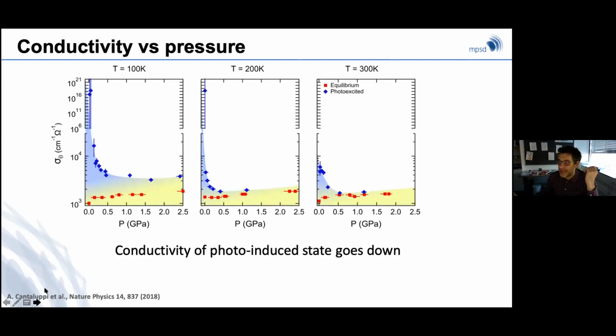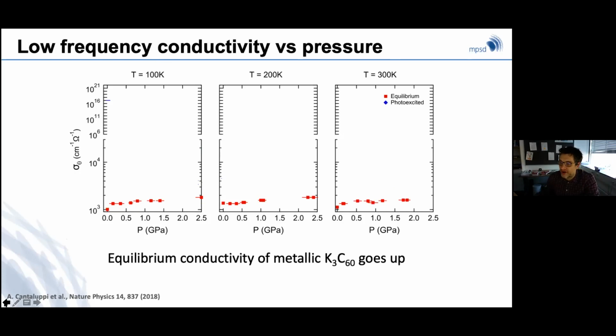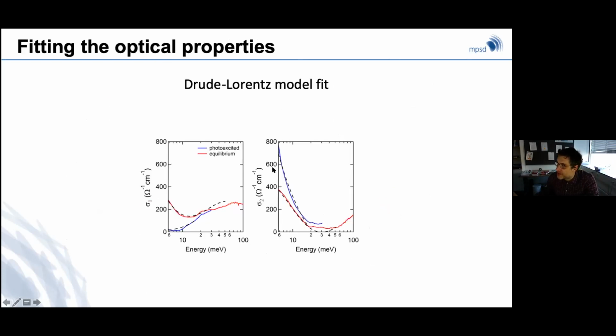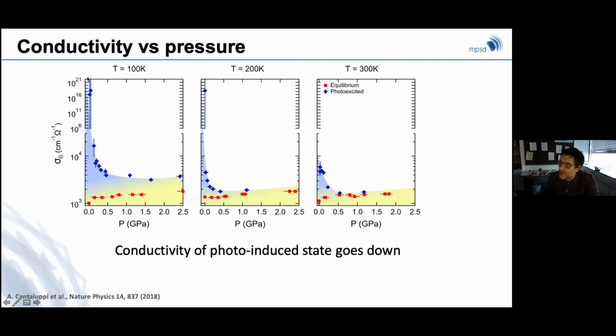But if we now go to the light-induced state at low pressure, you can see sigma 0 is basically infinity, plus or minus 10 to the 10. It's some number that diverges, and it can only be assessed to a degree of precision that depends on the lowest frequency cutoff of my measurement, so my ability to extrapolate to zero frequency depends on how low a frequency I can measure. But at low pressures, I can tell that at 100 Kelvin, sigma 0 is basically infinity, so rho 0 is basically 0.